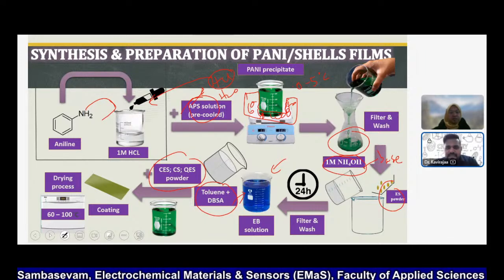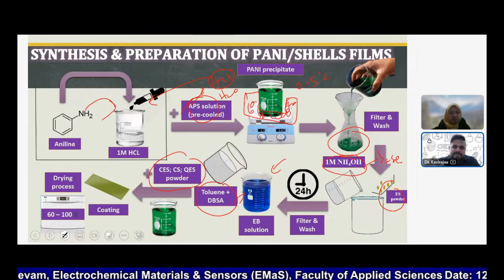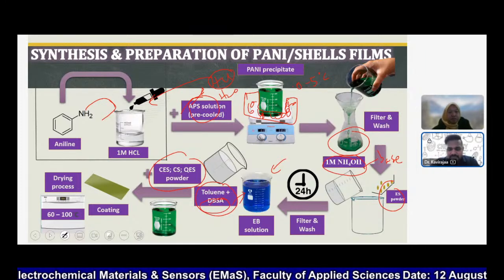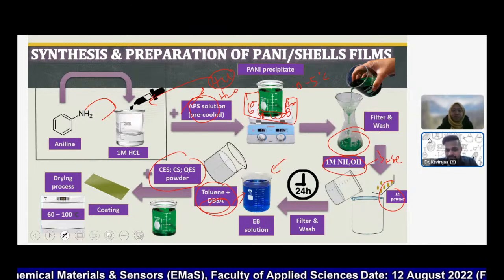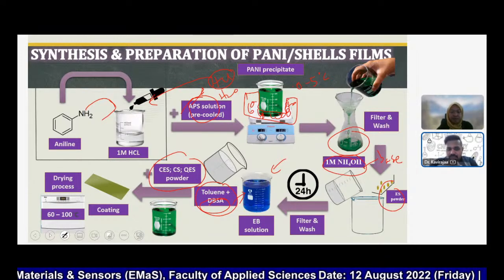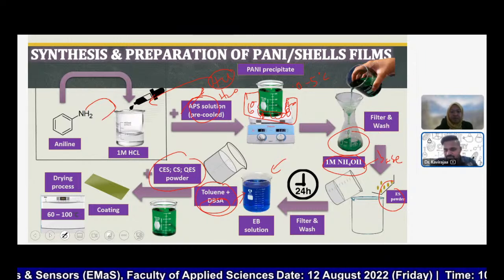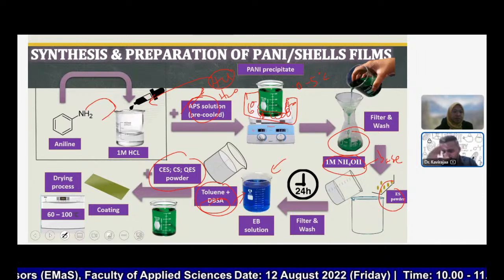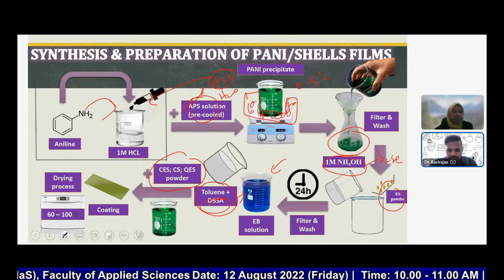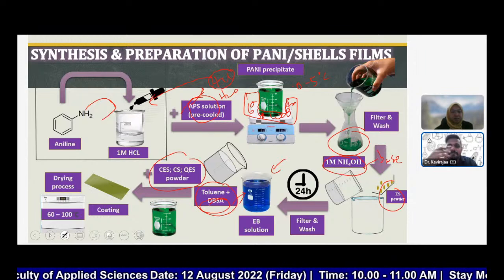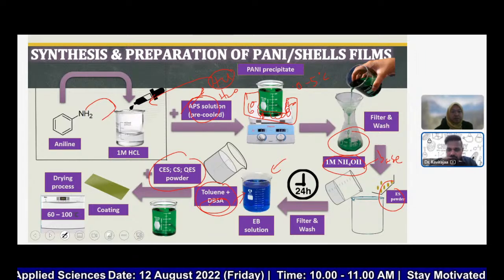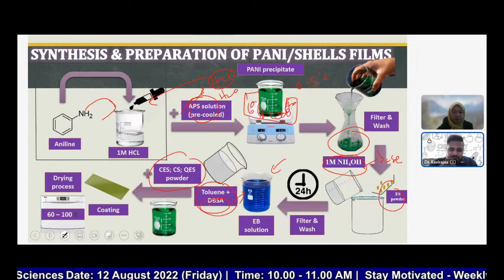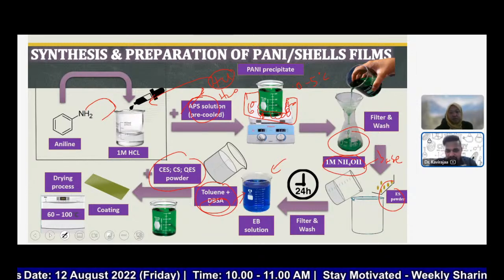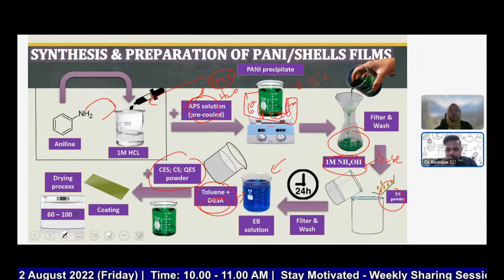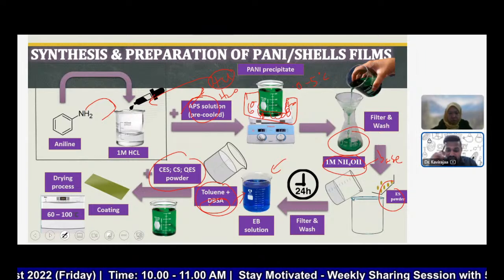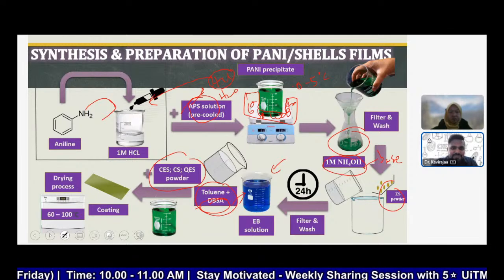Okay, here we are applying the ex situ method. If we want a processable polyaniline, which means a polyaniline that is soluble, because one of the major drawbacks of polyaniline is that it's not soluble. If we do a normal procedure like this, you will end up with polyaniline powder which is not soluble. We can just make it disperse. But our concern is to produce something that is processable, totally in solution form without any particle formation and so on. So that's why we actually have to add this DBSA at the initial stage itself.